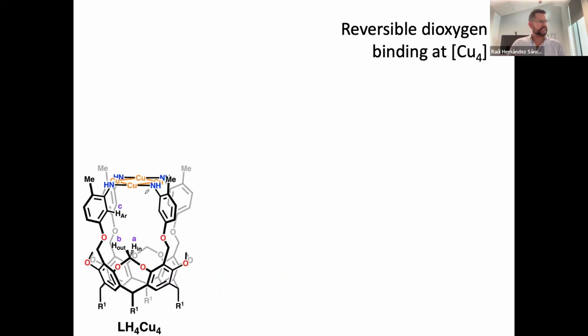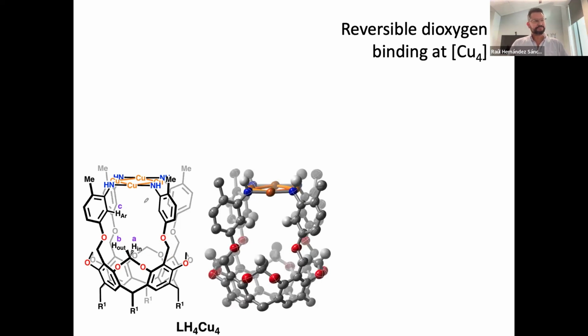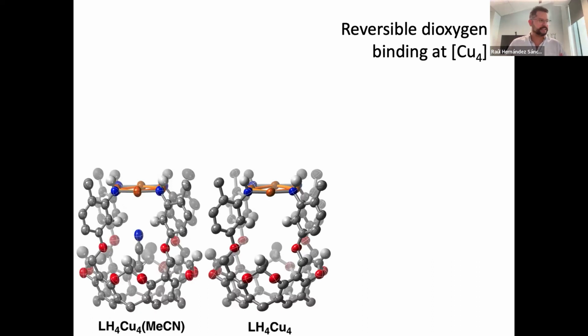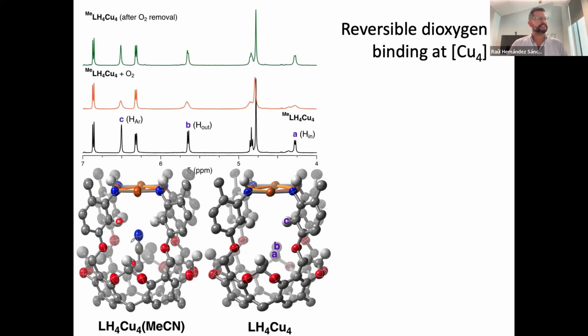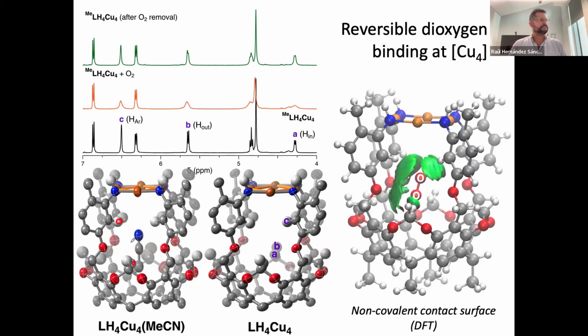Shifting to a slightly different ligand, the thing that we've changed is essentially just the size. We've introduced that linker and made this cavity slightly larger. And so by doing that particular change, we're able to host simple molecules like acetonitrile, something that maybe is not that interesting, but by hosting acetonitrile, we know which resonances shift, and specifically this one's pointing towards the acetonitrile molecule. If we test a more interesting substrate, in this case dioxygen, we see the shifting of those same resonances, A, B, and C. And so we see the reversible uptake of dioxygen. DFT tells us that it likely sits right there.